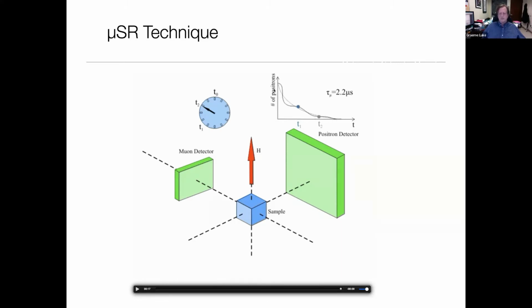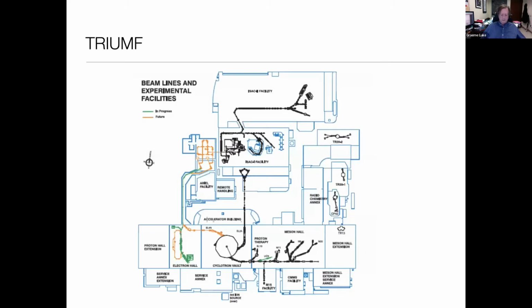But then this lifetime curve is superimposed on that, the projection of the spin on that axis. So if the muon happens to be pointing towards the detector when it decays, the positron is more likely to go in that direction than the opposite direction. And once we do this many millions of times, we have a nice curve that looks like so. I'll show you a better picture in a minute. Then from that, we can extract things about the muon spin polarization function.